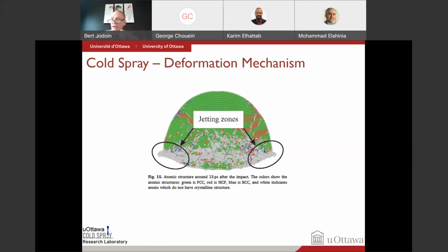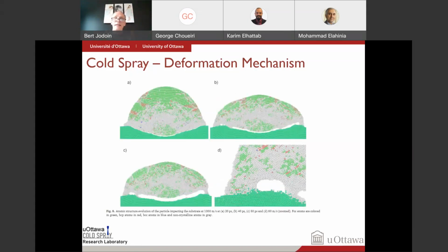It's so intense that you lose that crystallinity. You get lots of dislocation movement, creation, generation. And then you get those zones that now can flow very well. And some of them, as you can see here in the model, can bond with the substrate, and you can see that you have a good mixing of atoms. Eventually, after that, you're going to get recrystallization because this is only after a few picoseconds. It's a fast process. So in the end, they go back into their crystal structure with a refined microstructure at this very, very tiny zone. But these models allow us to figure out what's going on.